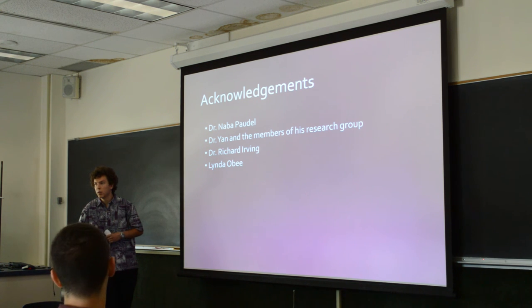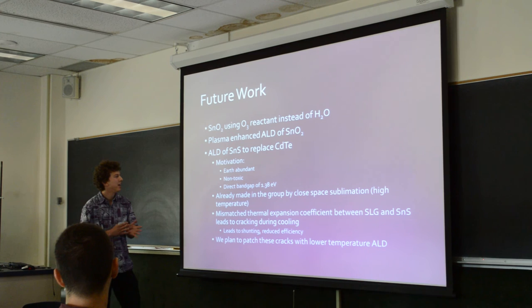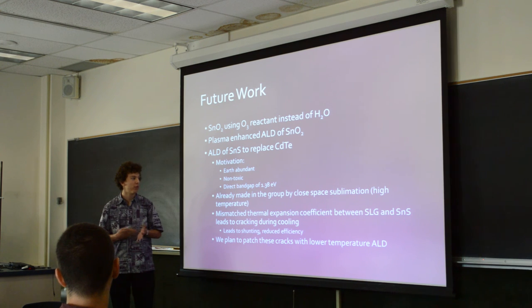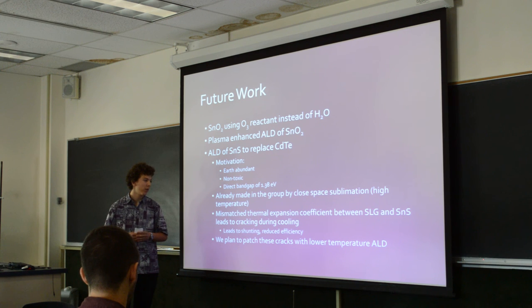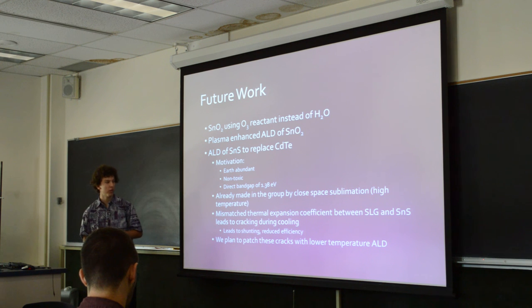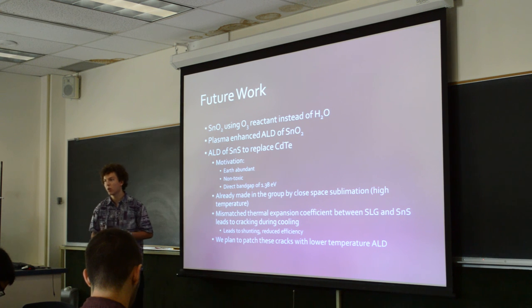Question: You had a slide talking about fixing cracks — can you talk about that? The tin sulfide — why do we want tin sulfide? Instead of cadmium telluride, it's non-toxic, earth abundant, and has a band gap that gives a higher theoretical efficiency than cadmium telluride. We already make it in our group via close space sublimation, but this requires high temperature and the mismatched thermal expansion coefficients between the glass and the tin sulfide lead to cracking when cooling. So by doing ALD at lower temperatures, we're hoping to catch those pinholes via ALD, which will reduce the shunting of the device.